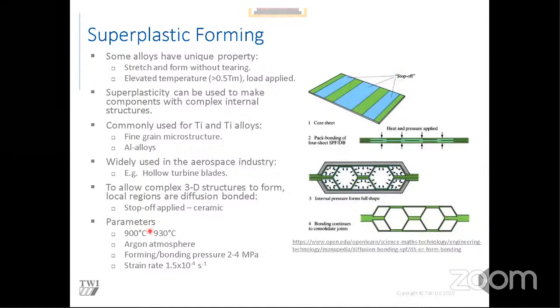So that's all enabled by a combination of diffusion bonding and your stop-off. This is typically carried out for titanium at 900 to 930 degrees C, in argon, with a gas pressure of 2 to 4 megapascals. The strain rate, which is very important for superplastic forming, is 1.5 times 10 to the minus 4 per second - a relatively slow strain rate.